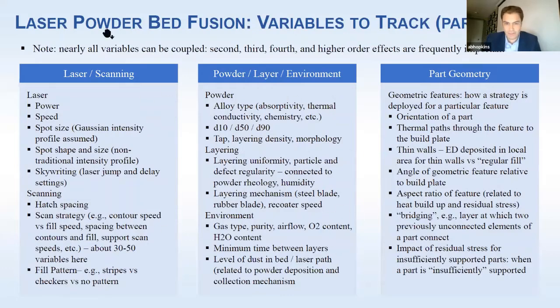And then, doing all this, the question is, if you are tracking all this, if you do have a stable parameter set, and by parameter set I mean powder, layering, scan strategies, beam spot size, the whole story, environment, then there are certain part geometries that you can create that warp and do not warp, that oxidize and do not oxidize, again, very material specific. Aspect ratios you can print and cannot print related to residual stress. This becomes, again, a pretty complicated problem. There are softwares out there that bring this into the thermoelastic regime. I'll get to those in the binder jetting portion. And they can predict shrinkage and warpage. Those are very interesting if they can work. Softwares kind of work, they kind of don't today. There are problems that still need to be solved.